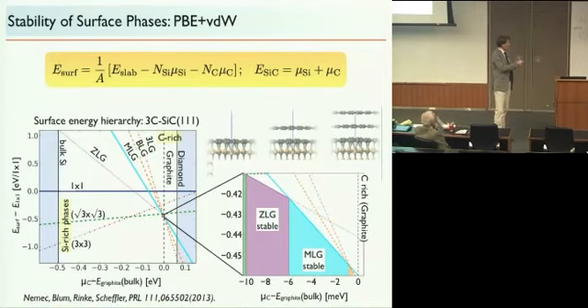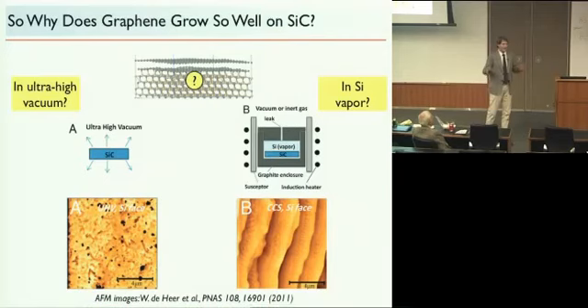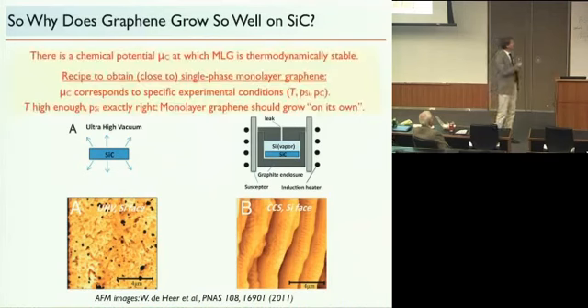I have to say that these energy differences here are very subtle. So this is certainly inside the error limits of what we can do from density functional theory today. But what this means is that there is either a stable phase or something that is very near thermodynamic stability. So in more practical terms, going back to the picture from the beginning, if the chemical potentials are meaningless parameters for someone, what it really means is that we can understand this by just looking at the formalism. If there's a chemical potential at which monolayer graphene is the most stable phase, then that will correspond to some experimentally accessible temperature pressure conditions, and we have to find these to know where monolayer graphene will essentially grow on its own if the temperature is high enough.